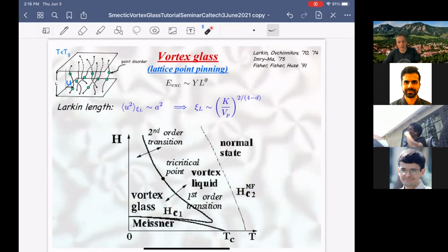And one way to analyze the stability of a crystal phase to point disorder is to do a Larkin analysis. The Larkin analysis is a criterion rather than a crossover. It considers the distortions of a perfect vortex lattice due to the point disorder, due to the random potential, and asks whether those distortions build up, let's say in 3 dimensions, for any infinitesimal or weak amount of disorder. Can they build up so much that the root mean square fluctuations become of order the lattice constant a? When they do, one can say that the vortex crystal phase has undergone an instability to a vortex glass state, or a state at least that doesn't break translational symmetry. It's no longer periodic.